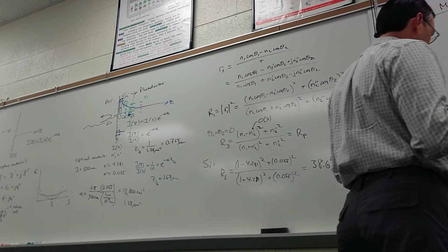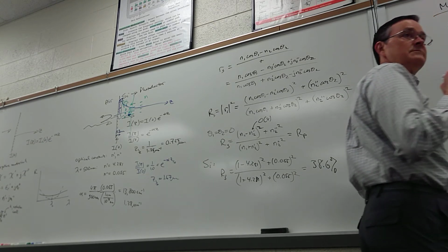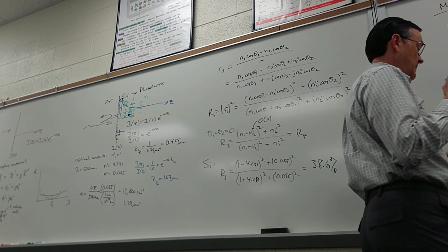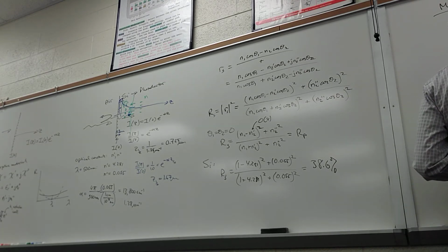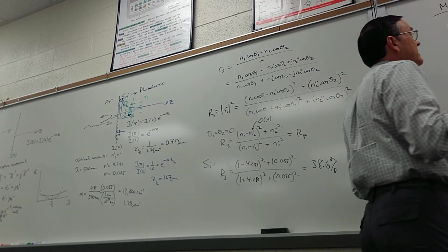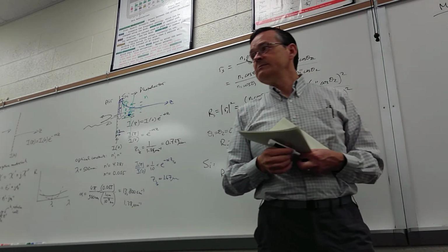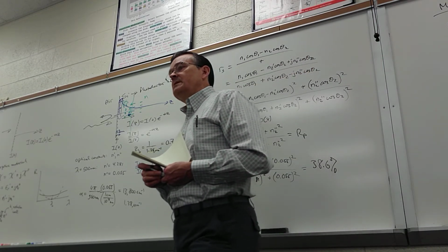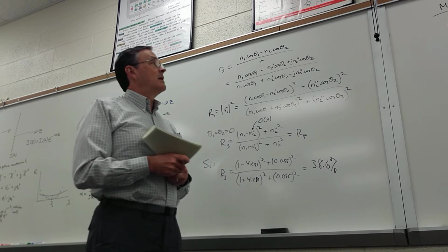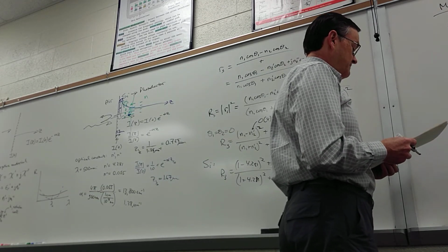The real part of the refractive index is 0.826. That's not very big. The imaginary part is 6.283. That's big. It's not absolutely gigantic, but it's big. The reflectance is 0.923. It's over 90% reflectance. Pretty good. It's not bad at all. And it's cheap, so that's why we have such mirrors in our bathrooms.